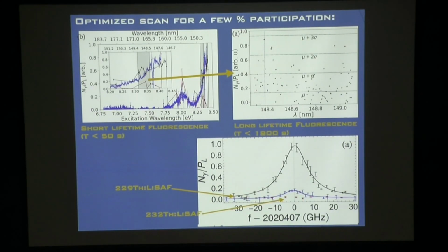And we saw a much bigger signal. It turns out that the crystal we had been using for all these years, only about 1% of the thorium participated. But we had 3 other crystals on the shelf. And in all 3 of those crystals, about half of the thorium-229 participated. So we chose the wrong crystal 4 years ago. I don't know. That's what you do when, sometimes things aren't easy.